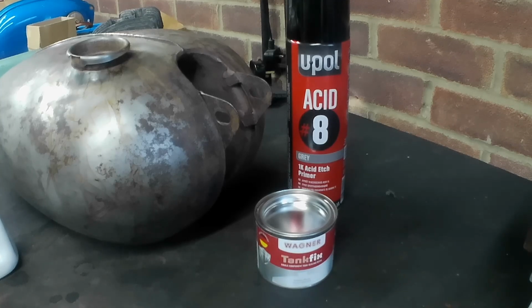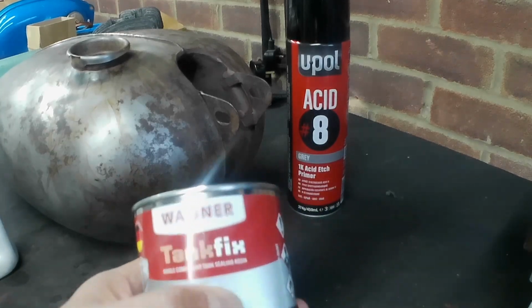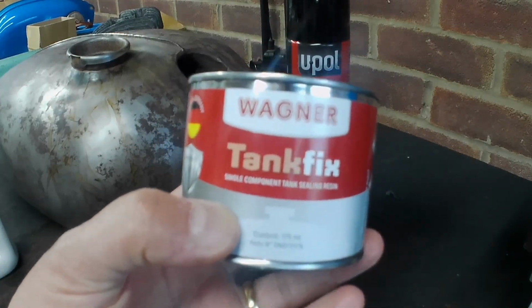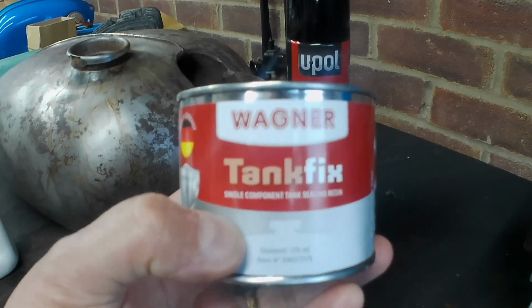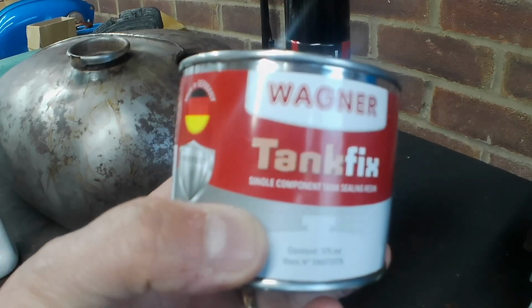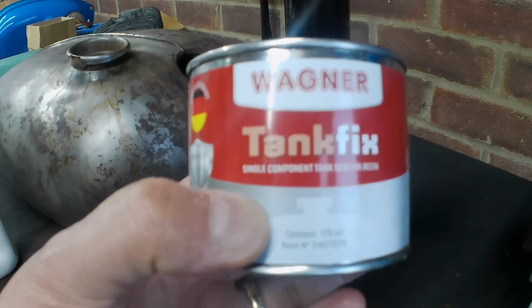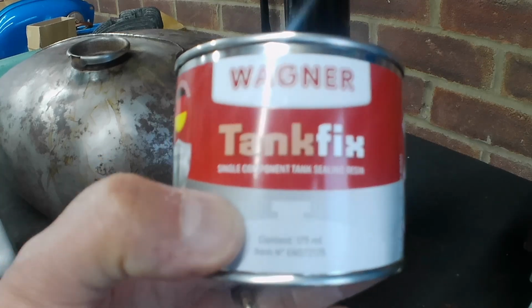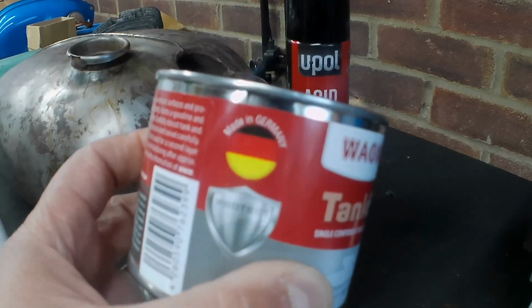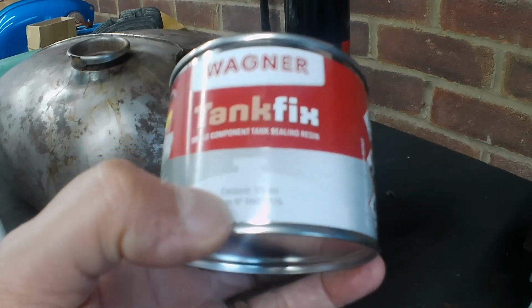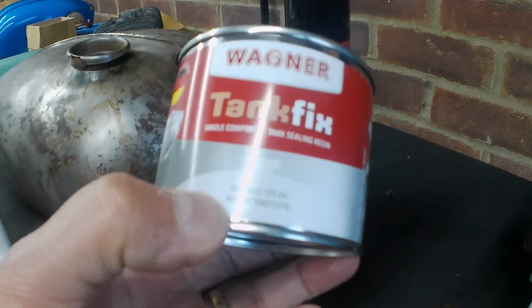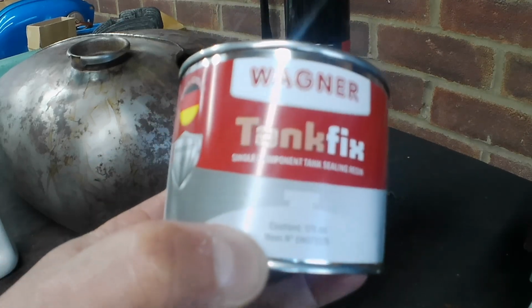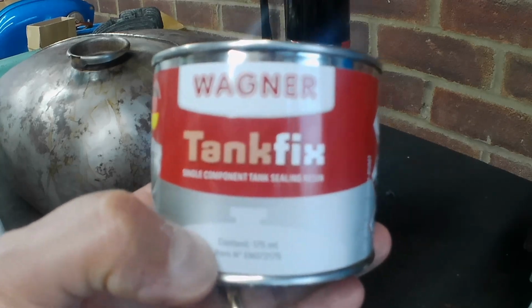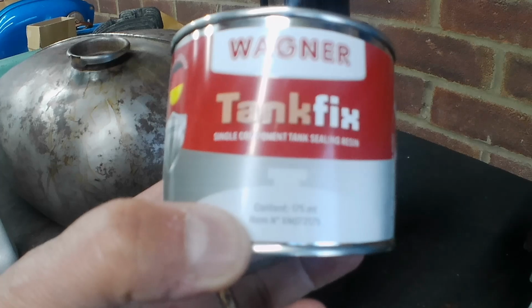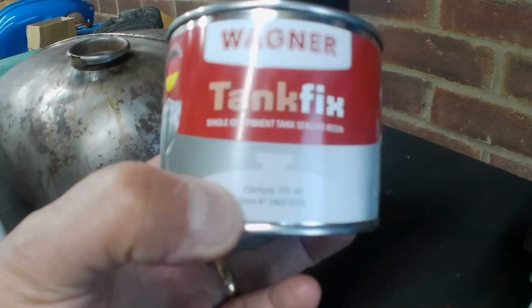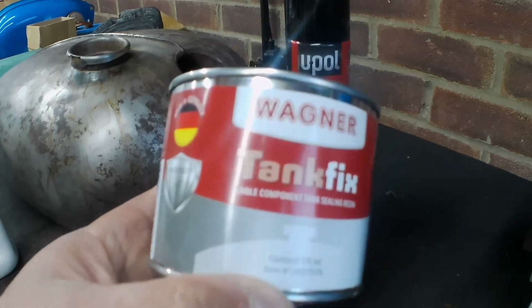And once we've completed the corrosion removal, we'll be moving on to lining the tank, and this is what we're going to use. We'll chase out the moisture with methylated spirits, give the tank a good dry, and crack on with this stuff. I've used this a few times before and had good results. Tank Fix single component tank sealing resin, made in Germany, and this is 175 millilitres. I nearly said litres. 175 litres would do a 1,000 litre fuel tank, which would be pretty big. I think that would be a long range Bantam. You'd probably struggle to get your legs either side of the tank though, but there you go. So 175 millilitres, enough for a 10 litre tank. So we're going to have plenty to do our tank.